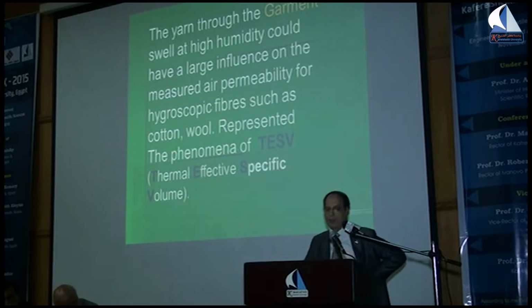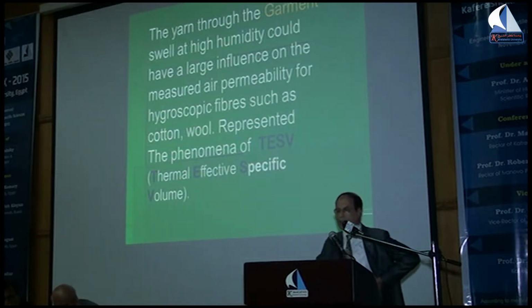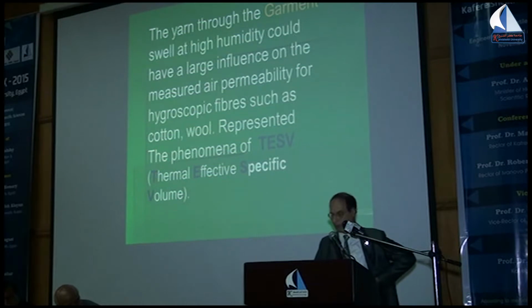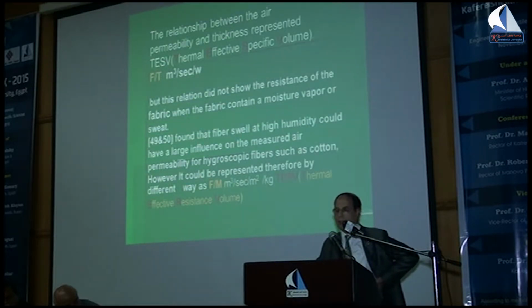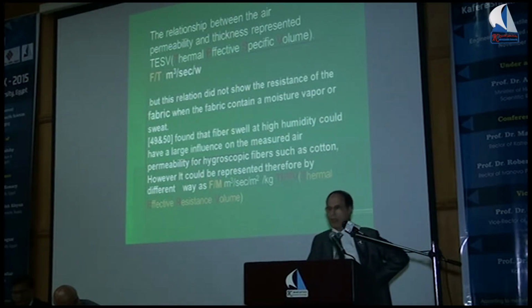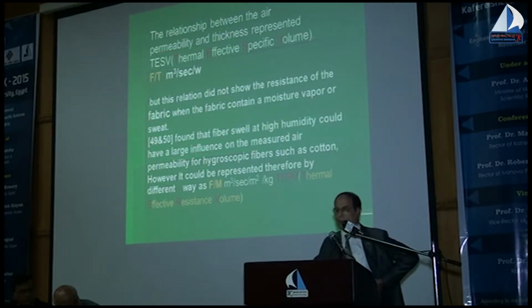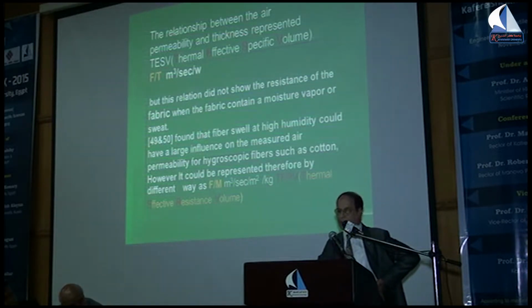The yarn swelling through the garment at high humidity could have a large influence on the measured air permeability for hygroscopic fibers such as cotton and wool, representing the phenomenon of TESV, the thermal effective specific volume. The relationship between the air permeability and thickness represented the thermal effective specific volume, but in my opinion this relationship does not show the resistance of the fabric when the fabric contains moisture, vapor, or sweat.